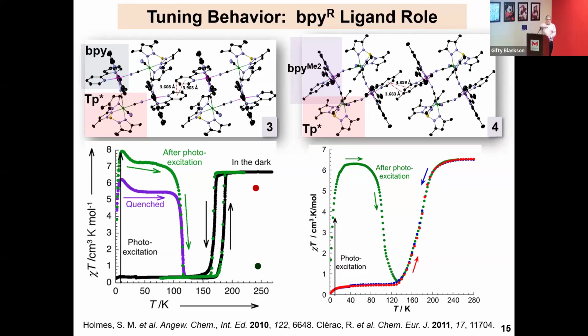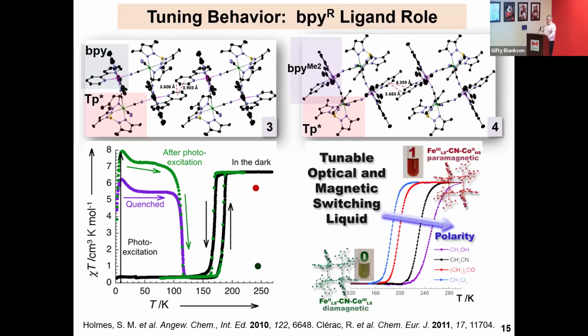You see that the hysteresis for here, with those closer contacts, goes away as they become further apart and separated. We can still access the photochemical state, although it looks a little different at low temperature. That's an area of active research. The thermal hysteresis went away, but more importantly, we have a compound now that's soluble, whereas the compound on the left is insoluble. We can dissolve it in solvents, and as we change the polarity of the solvent, we can change where the electron transfer happens. That is, high dielectric strength solvents, particularly methanol, hydrogen bond to the terminal cyanides and shift the redox potential to a very high value. And you see a very high temperature for the electron transfer.